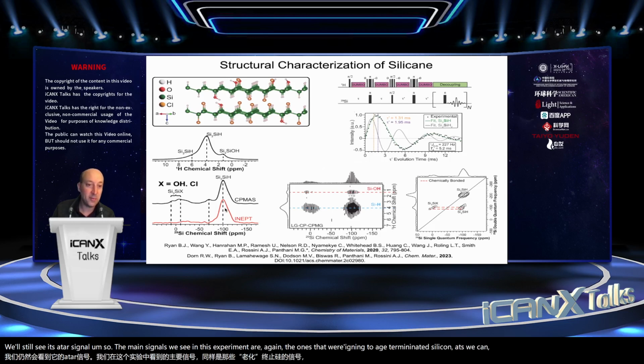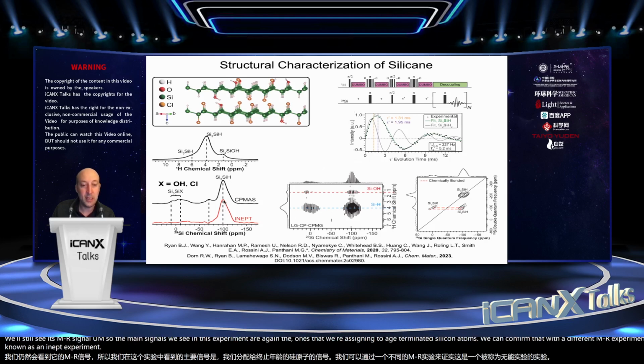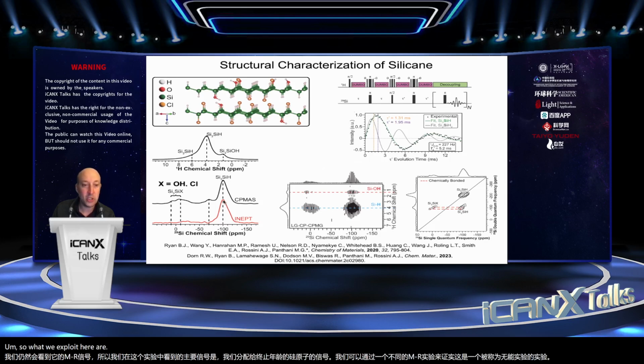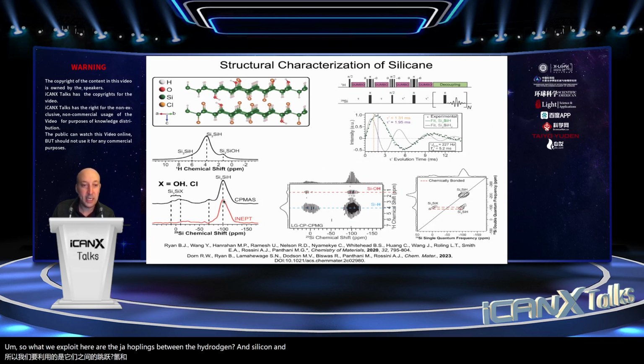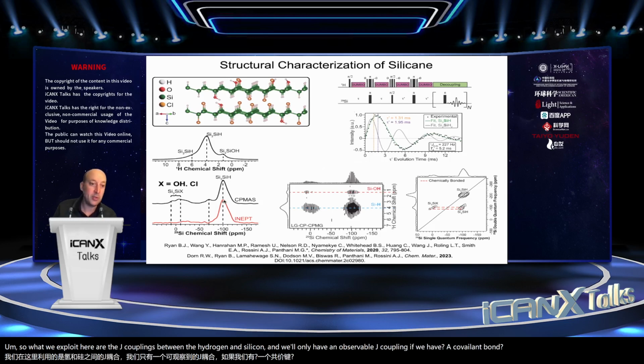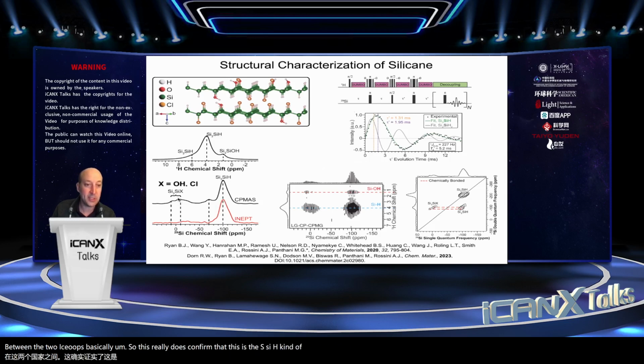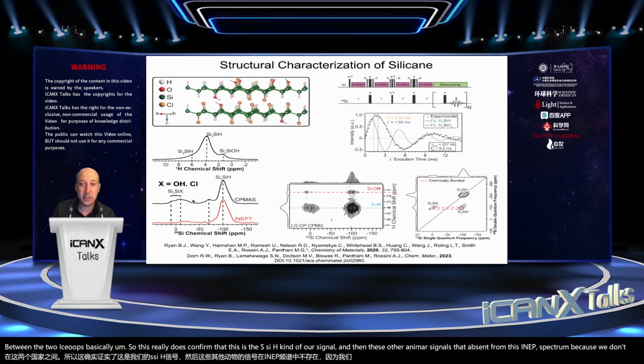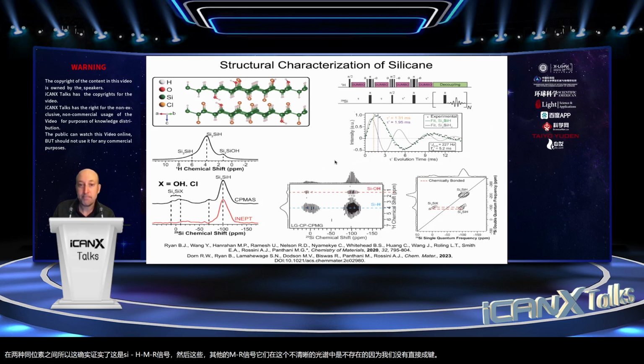We can confirm that with a different NMR experiment. This is known as an INEPT experiment. So what we exploit here are the J couplings between the hydrogen and silicon, and we'll only have an observable J coupling if we have a covalent bond between the two isotopes, basically. So this really does confirm that this is the SiH NMR signal. And then these other NMR signals are absent from this INEPT spectrum because we don't have a directly bonded hydrogen.